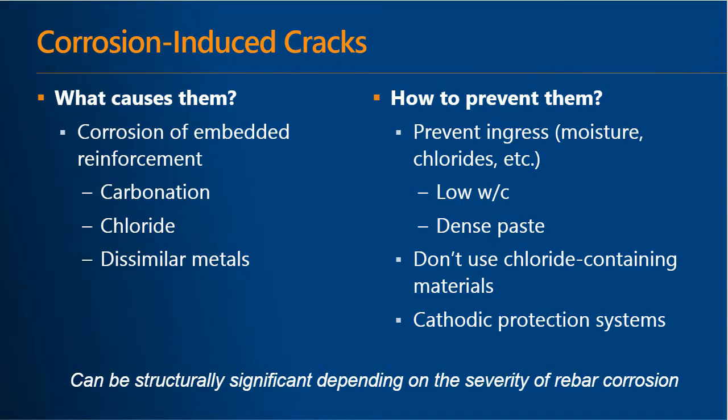You could also get chloride-induced corrosion, which I think is most common and what most people think of initially, especially with the use of chloride de-icing salts. But you can also get dissimilar metal corrosion as well. One of the ways to prevent corrosion-induced cracking is, one, don't let moisture and/or chlorides get into your concrete. And also don't use chloride-containing materials such as admixtures and de-icing salts.